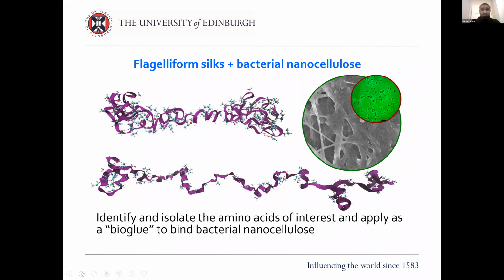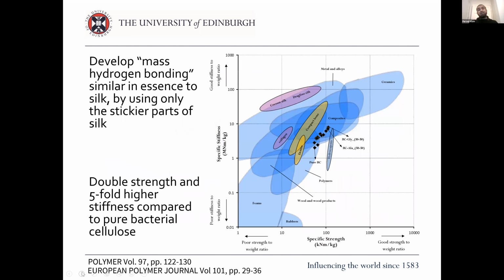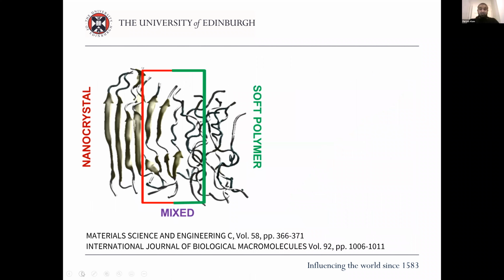And the best one, in my opinion, to use is bacterial nanocellulose. It's a very difficult word to say for some reason. Bacterial nanocellulose, because it is 98% pure, and it doesn't have the lignin and the other sort of impurities in the same way that nanocellulose from wood or from tree, woody sources, has. So we did that, and we actually managed to double the strength with respect to density and increase by 5-fold the stiffness with respect to density. So the specific strength and specific stiffness respectively, as compared to normal bacterial cellulose sheets. And they are, of course, then composites, because the monomeric amino acids form essentially the matrix, or the bioglue that holds together the fibers.